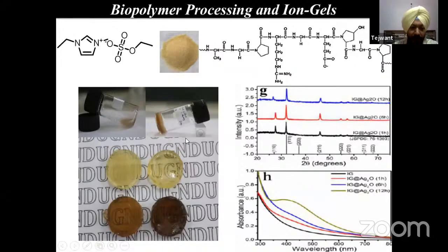Now one can form the gel of gelatin by using water as the solvent. That is called a hydrogel. I have shown a photograph of the hydrogel over there, this one. The second one is the photograph of the ionogel. Now the problem was that once you keep the gelatin ionogel in open atmosphere, because gelatin is a biopolymer, it used to be degraded by the bacteria present in the open environment. So the gel was not stable, especially in the presence of bacteria.